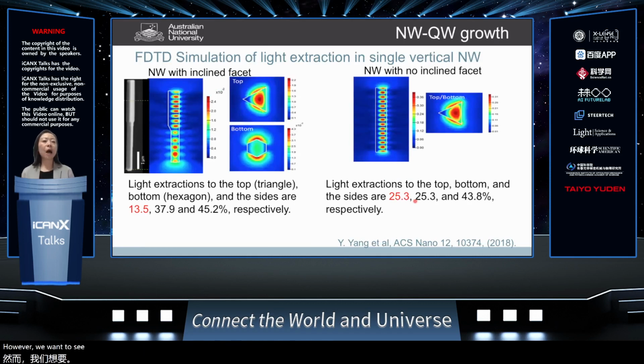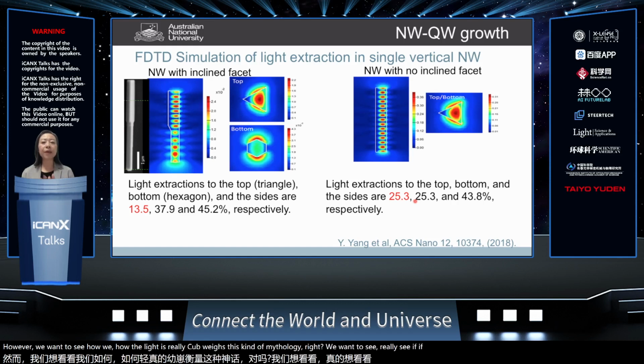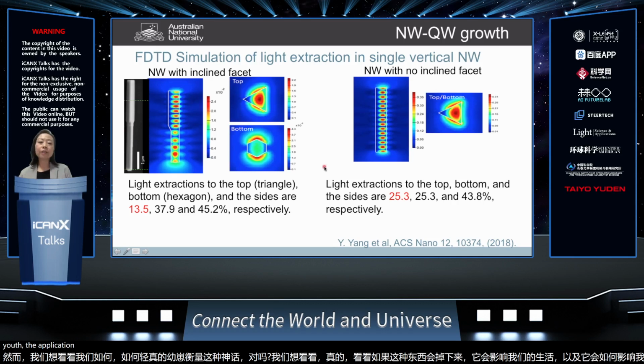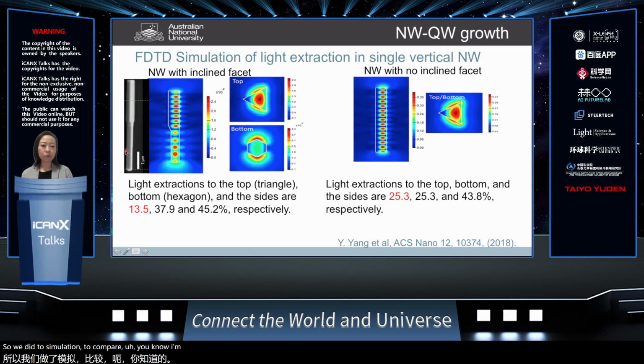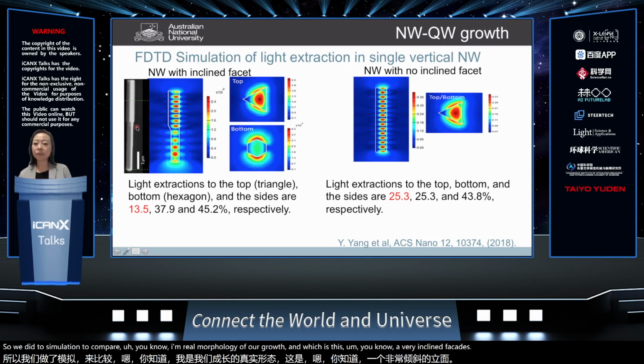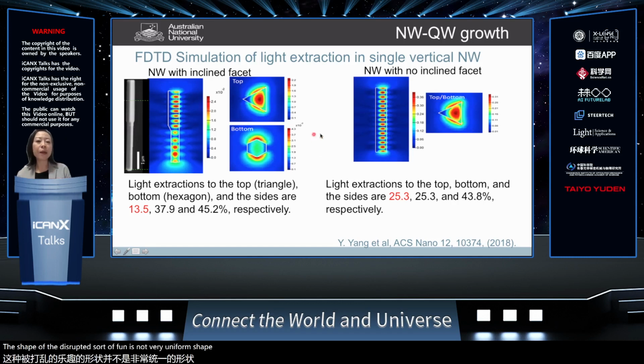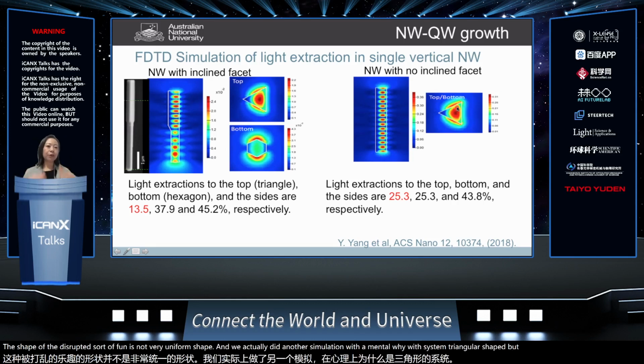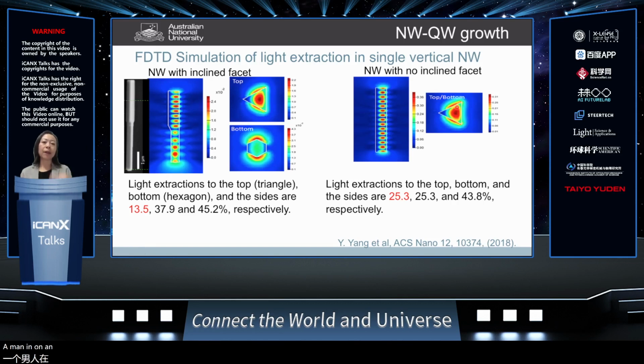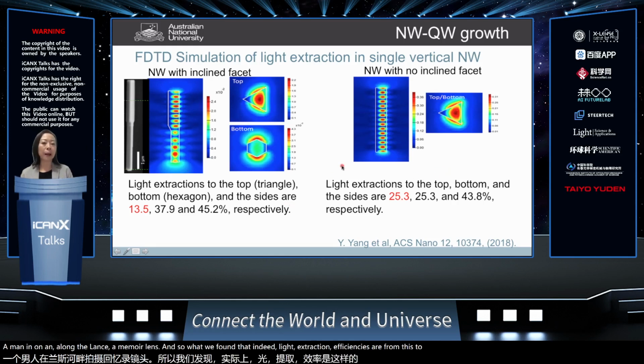However, we want to see how the light is really affected with this kind of morphology, right? We want to see if that kind of morphology will affect our light emission, how that will affect our light extraction from nanowires, because it's very important for LED application. So we did two simulations to compare a real morphology of our growth, which is this very inclined facet shape, a disrupted sort of not very uniform shape, and another simulation with a nanowire with this triangular shape but very uniform along the nanowire length. And what we found is that indeed light extraction efficiencies from these two morphologies are very different.